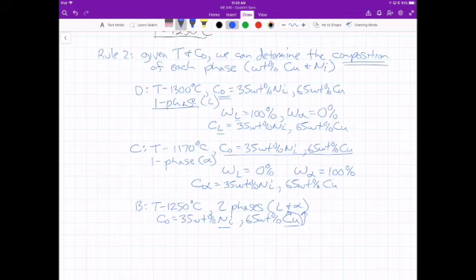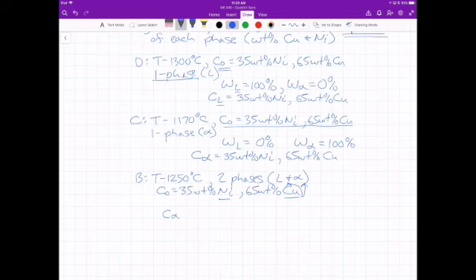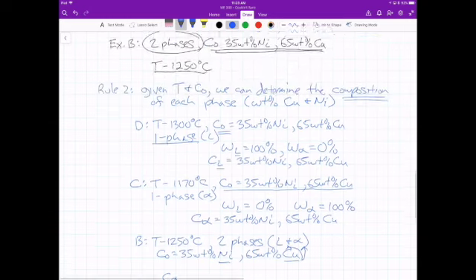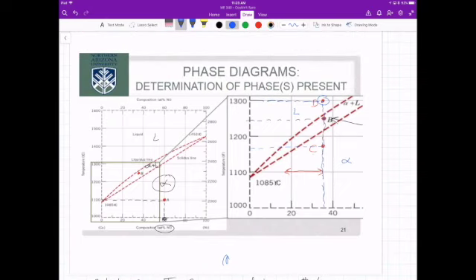So since we have two phases, we have two concentrations. We have the concentration of alpha, and we have the concentration of the liquid. So this is really easy. When we have two phases, we just have to go horizontally until we reach the phase lines. We go horizontally until we reach a phase boundary. The phase boundary on the left is the liquid phase boundary. The phase boundary on the right is the solid phase boundary. To measure the composition, the amount of nickel and copper in each of these phases, we just go straight down from the phase boundary, and that gives us the value for each one. If I go to the left, I hit the liquid. This is the concentration of nickel in the liquid. If I go to the right, to the solid line, this is the concentration of nickel in the solid.